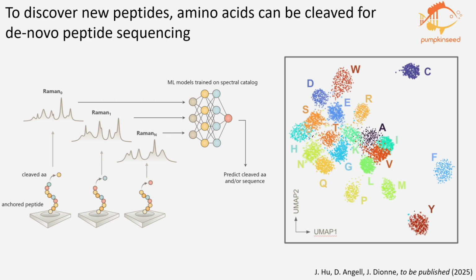Okay, so what we're doing is this Raman spectroscopy aided by silicon CMOS compatible resonators that boost the electromagnetic field, so that we get Raman enhancements by at least 8 orders of magnitude. And the idea is that you can take these peptides, remove them from a sample, like a patient tumor sample, and even though the number of peptide sequences is extraordinarily diverse, they all have a C-terminus and they all have an N-terminus. So that C-terminus can be bonded covalently to the surface of our chips just using click chemistry. So we orient the peptide, and then we collect the Raman signal dynamically as we're cleaving off the N-terminal amino acid.